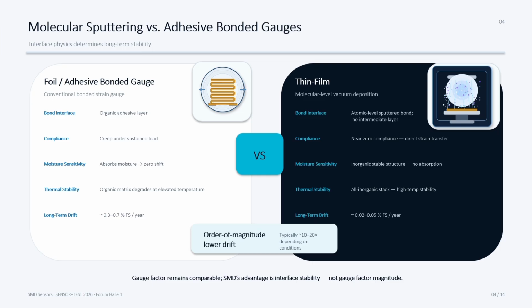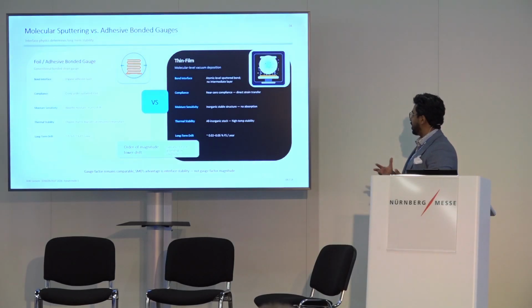This slide is about the thin film design choices: glue versus sputtering, depending on what we want to use. An adhesive bonded foil gauge uses an organic layer between the gauge and the metal, and that organic layer creeps under sustained load. It can absorb moisture, thermal stability becomes an issue, and long-term drifting can occur.